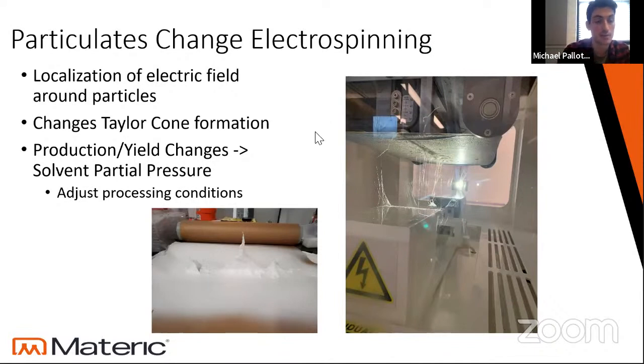Next are changes in the Taylor cone formation. In a lot of cases, we'll add salts to our polymer solutions to help the conductivity. Although that helps the conductivity, you do ultimately change the spinning parameters. I use salts as the preliminary example, but the same thing happens with nanoparticles or metal organic frameworks. You end up changing your spinning parameters and the way the Taylor cones are created, so you might need a different voltage applied to make sure that the Taylor cones stay stable. Otherwise, you might not have the long, strong nanofibers required for the mechanical purposes you need in a final product.